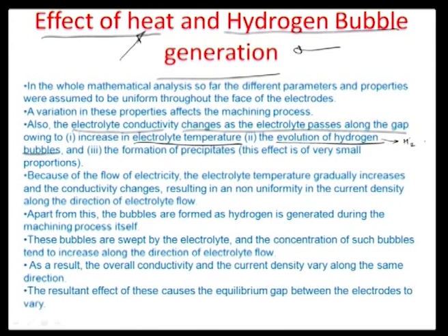This hydrogen is not able to go anywhere because the gap is too small, and it simply gets dissolved within the electrolyte. So, this further changes the conductivity, in fact it decreases the conductivity because of dissolution of the hydrogen. And then, of course, there is a formation of precipitates, because the process of electrochemical machining concerns carrying out material and generating a compound which is not dissolvable anymore. So, it precipitates into the solution, that is the prima facie requirement of an ECM process. This would impose a change in local conductivity because of circulation of this small debris, the so-called precipitate, which is coming out into the ECM electrolyte.